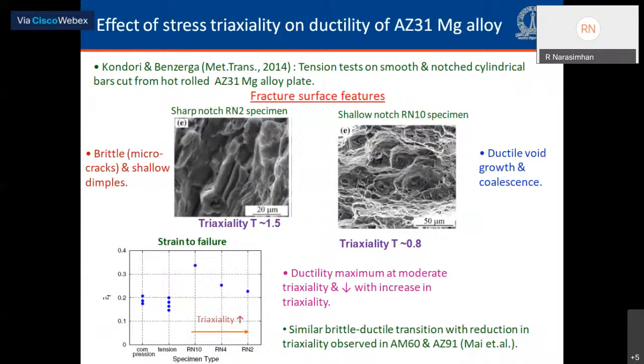Let me show one very important result from the literature which would actually motivate our work. This is a study on the effect of stress triaxiality on ductility and the failure mechanism in a rolled AZ31 magnesium alloy, from the work of Kondori and Benzerga. They did tension tests on smooth and notched cylindrical bars cut from a hot rolled AZ31 magnesium alloy. What you see in this slide is the fracture surface corresponding to a sharply notched Rn2 specimen,